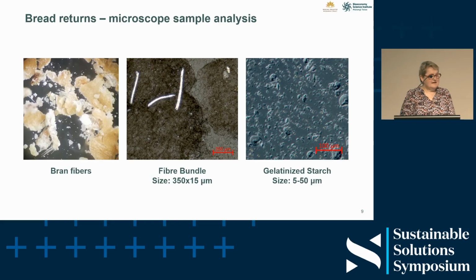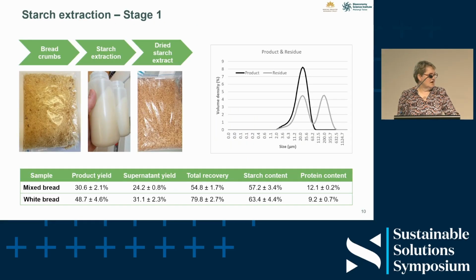Then just quickly, the bread returns were examined under the microscope. In the centre picture, basically you've got the bread matrix with some starch visible, but you'll see in white there's sort of like a plate-like structure and then long strings of the fibre. Because they were quite a bit larger than the starch granules, effectively, after we'd done an enzyme digestion, they could just be filtered out. So, starch extraction, different methods were tested and developed to extract the starches, and then the preferred method was scaled. This was just initially in the lab.